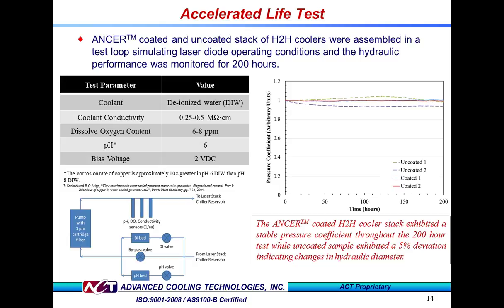Pete? Thanks, Billy. Next, we test whether ANCER coating can provide stability in hydraulic performance over a 200-hour test. Again, test conditions are listed on the left. Note that the pH of 6 was selected because the corrosion rate of copper is 10 times greater at pH of 6 than at pH of 8 for DI water systems.